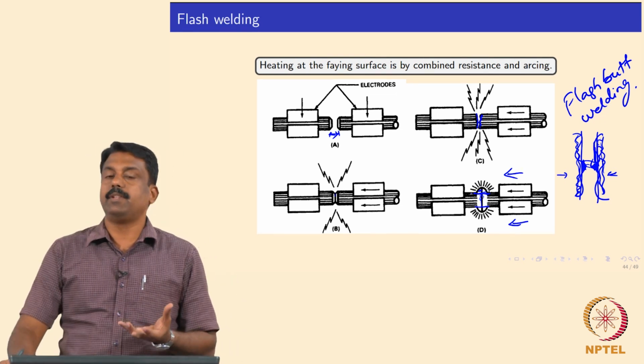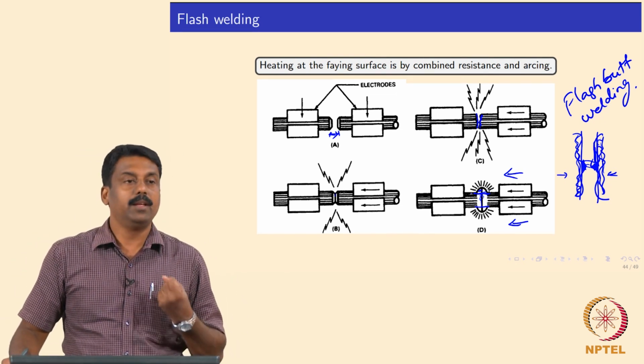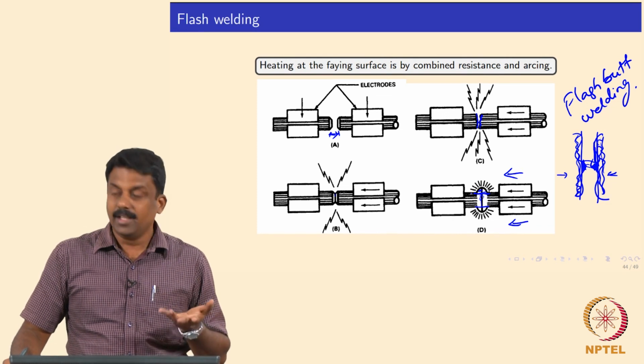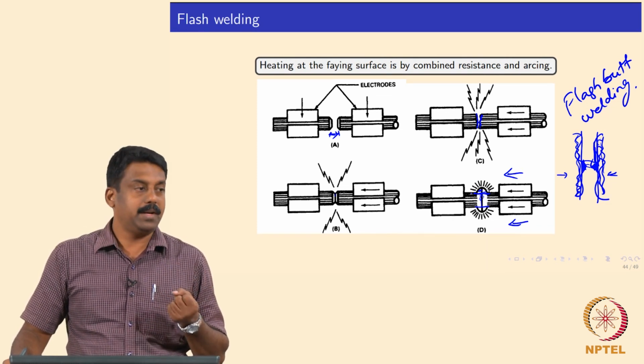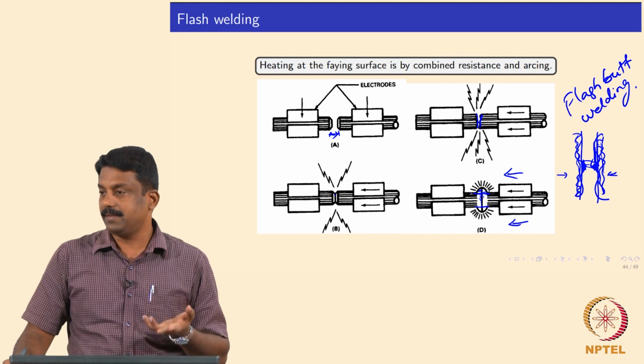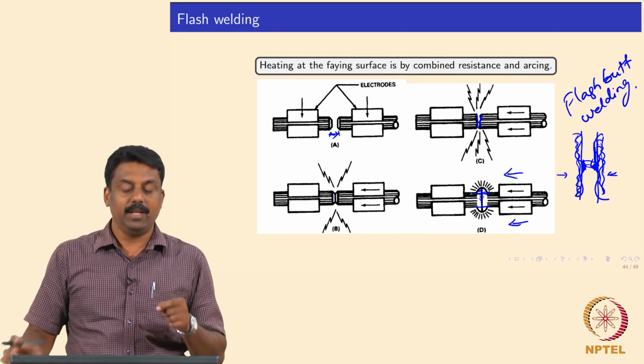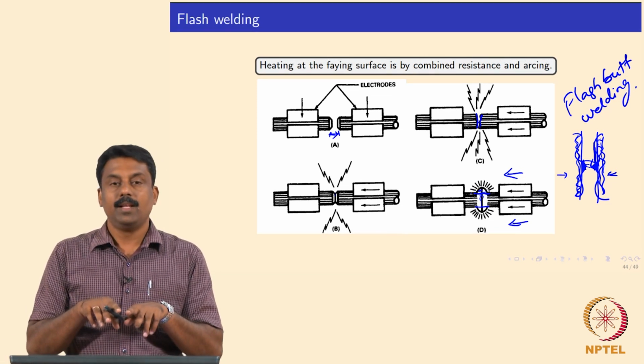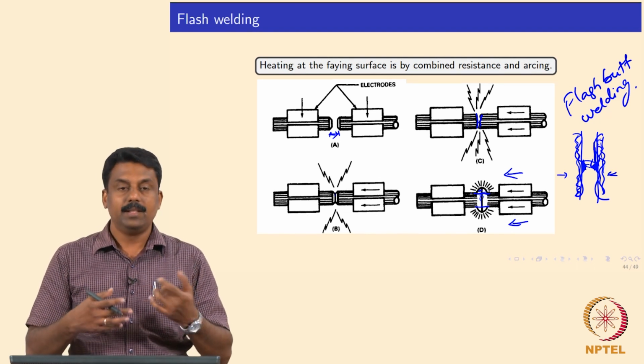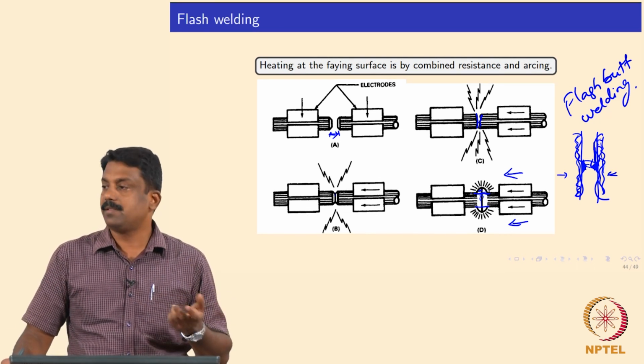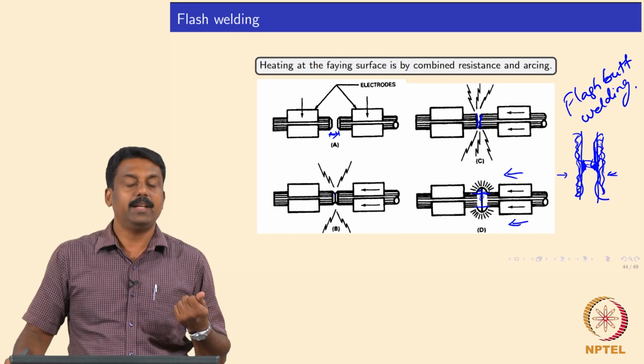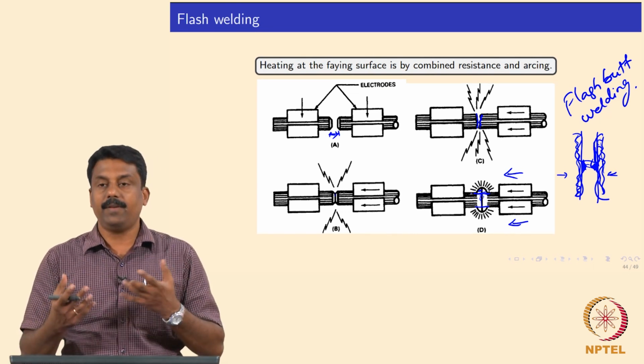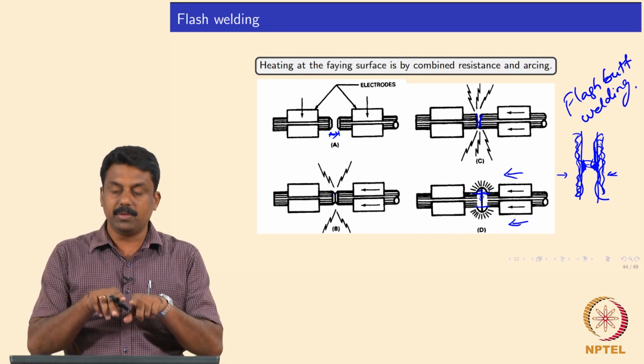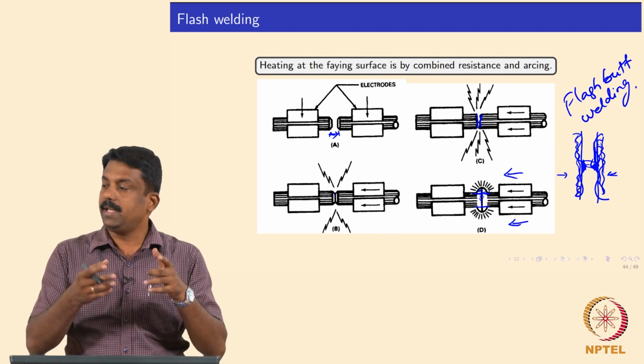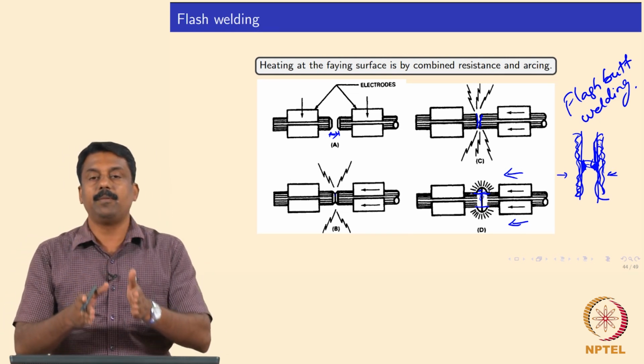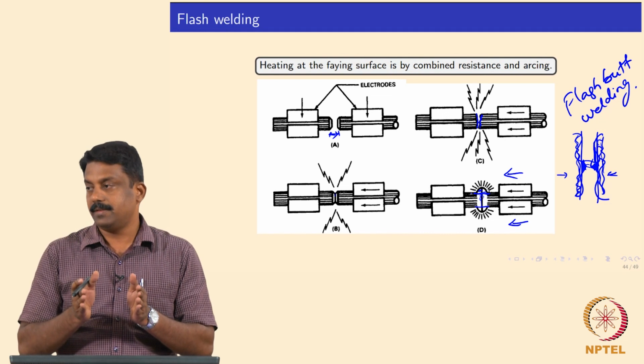There are a lot of advantages of this process. Advantage one is surface preparation. You do not need to prepare the surface, so you will have to bring it together. Even if the surface is rough, or you have a lot of oxides, it does not matter. Surface roughness can be overcome, because the moment you start arcing, you will end up melting the surface, and you will make a uniform liquid layer at the interface.